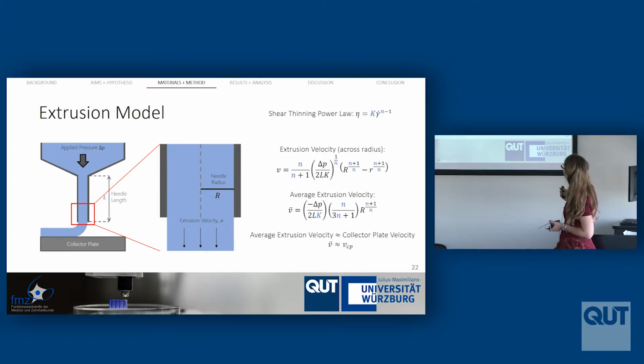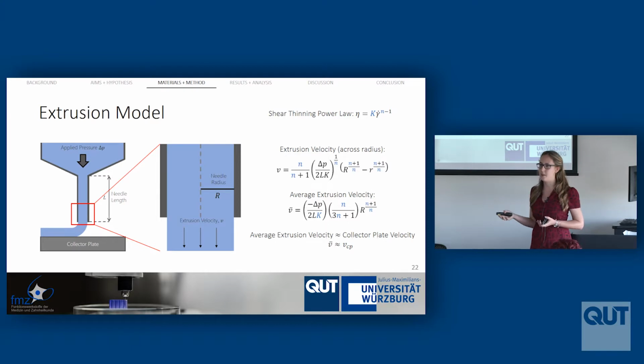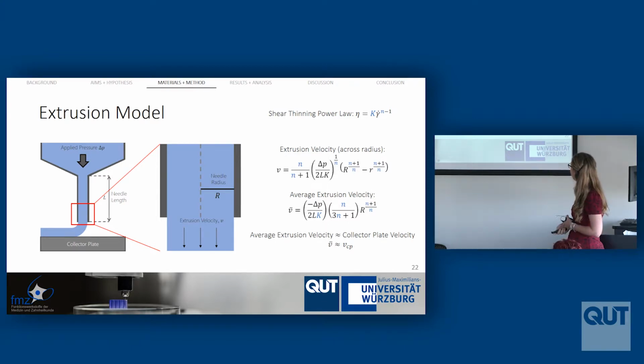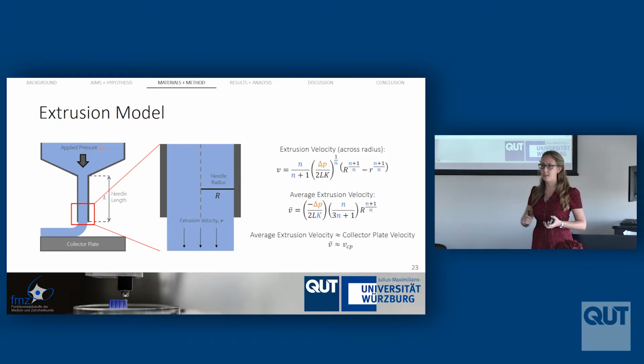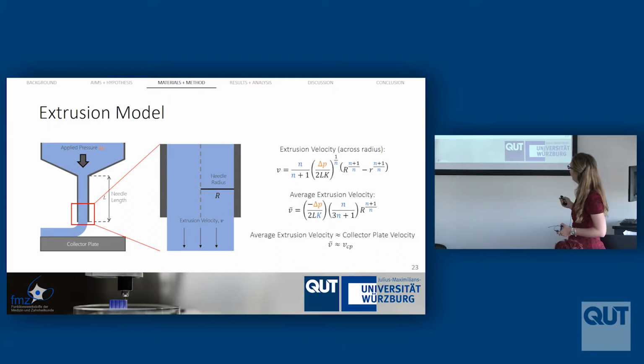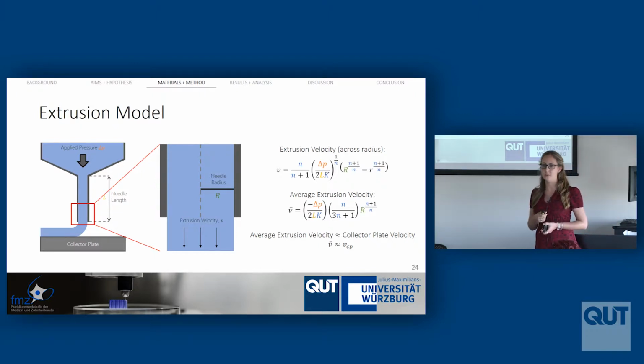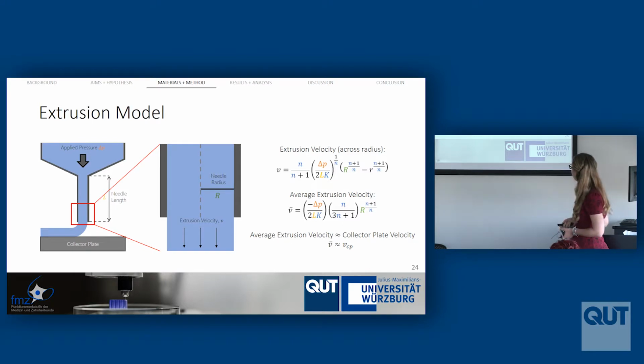Now I told you in the shear thinning diagram we could use an equation to model that. We get 2 nice little numbers from that, K and N, and so they pop up in these equations here all the time. But they're just fundamental numbers that we get from those graphs from the measurements, and so that's a really easy procedure for us. We also need the pressure. So this is looking at what is the pressure that we're applying on the bioprinter. Well, we've got a little nozzle and we kind of up and down that as we want. So that's our delta P, our pressure that we apply. And then we've also got the length of the needle and its radius. And so these are just fundamental to whatever needle that we've purchased for our bioprinter.